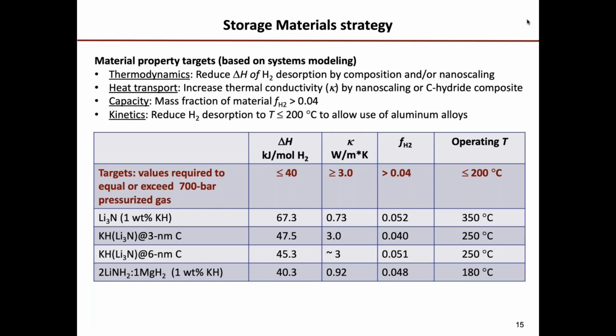So you can see in the red in this table, these are the values that we're targeting. And if you go further down, you'll see some of the materials that we originally looked at in HyMARC. For example, the bulk lithium nitride with a little bit of potassium hydride doped in there to improve the kinetics. Obviously, the enthalpy of desorption there is way off from what we want. If you put that into a 3 nanometer porous carbon host, you have a big drop of about 20 kilojoules per mole. And simultaneously, you have a factor of 4 increase in the thermal conductivity. If you broaden those pores, make them bigger up to 6 nanometers, you have a little bit further improvement in the enthalpy, and you maintain that attractive high thermal conductivity. So that's probably about the limit that we can go to with the lithium nitride, lithium amide system.